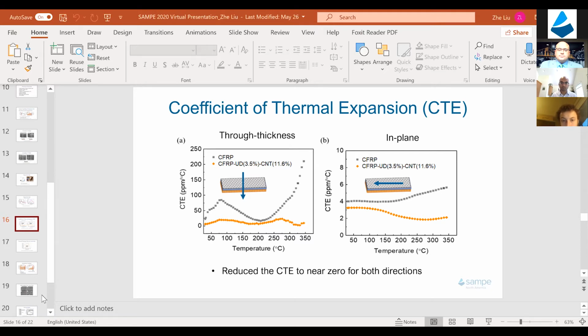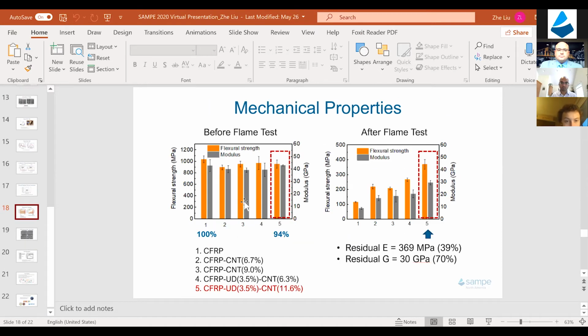Then we tested the 3-point bending for mechanical property with and without this thermal shielding layer. For the first coupon, without the thermal shielding layer, the mechanical property is around 1000 megapascal. This one is our baseline. After we calculate the 3-point bending strength with the shielding layer, the mechanical property sustains around 94% compared to the baseline. There's a little bit of a drop because we include the thickness of the shielding layer in the calculation, which means our sample is thicker than the baseline. So if we compare the force, they should be the same. That's my answer. Great, thank you.